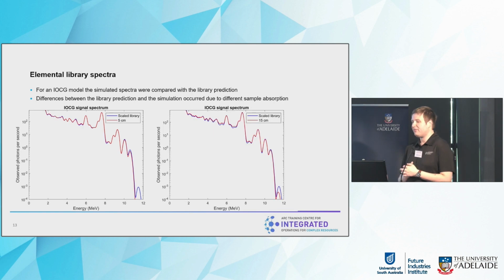So why do we want these elemental library spectra? It's because they can help us evaluate the compound material. So here we've scaled by the relative weight composition the elemental library spectra for the iron ore and copper gold ore, and we compare it to the previous compound material thickness measurements. We can see for the 5 centimeter case on the left, there is a good match in the overall spectrum, meaning there is a good prediction.